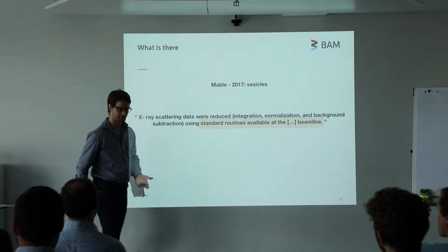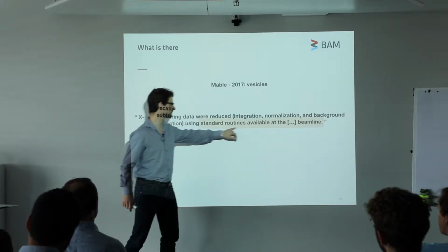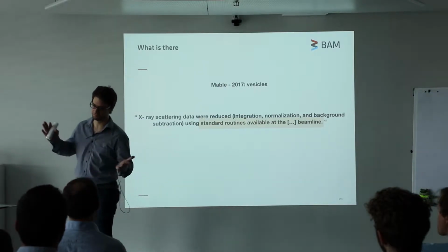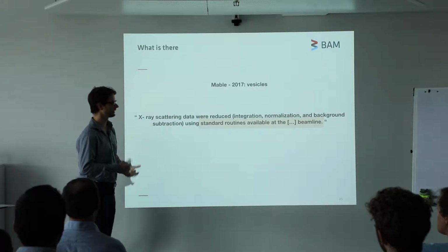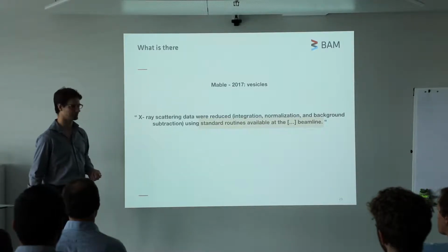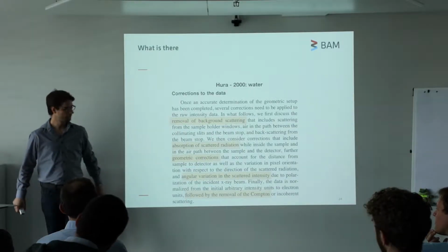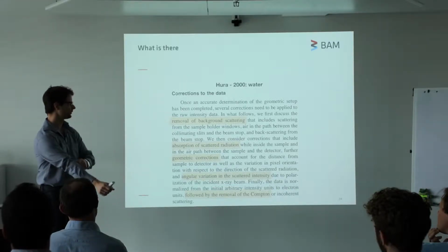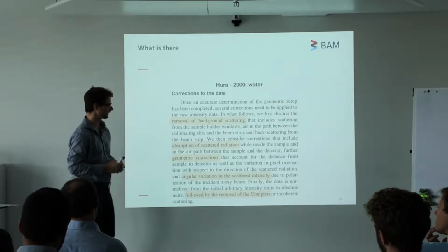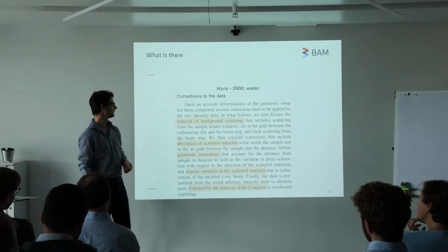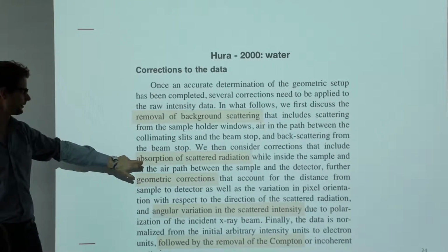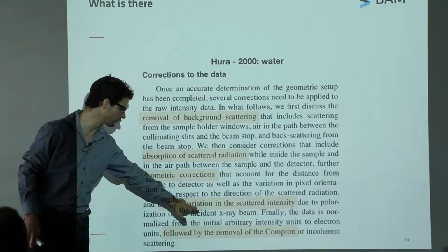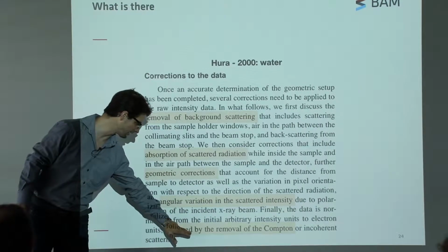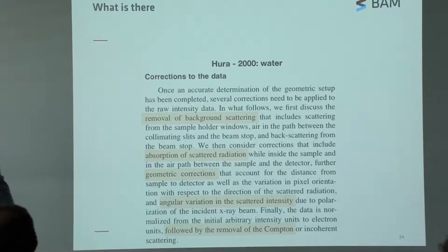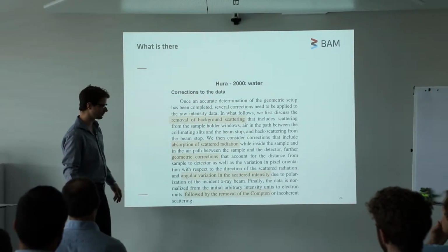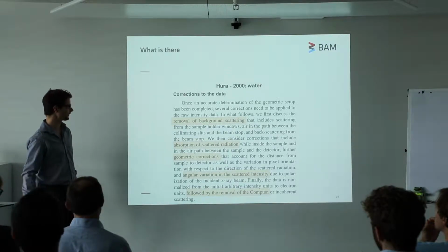Many people just use text to describe their data corrections, so they say things like, well, we just use whatever was available at the beamline, which is in principle fine, except that I then need to go and look at what the beamline does to find out whether I can trust their data or not. This one worked quite nice, which I regularly cite. They try to get a good small and wide angle scattering pattern for water. And they removed background scattering, direction-dependent absorption, geometric corrections. They did some more angular variation corrections, and removal of the Compton or incoherent background. And this is the first paper where I really see people, for X-ray data, to subtract the incoherent background.